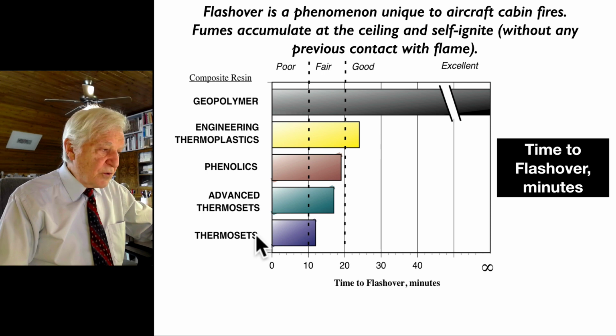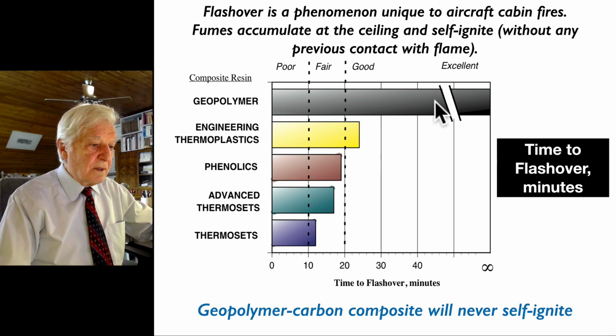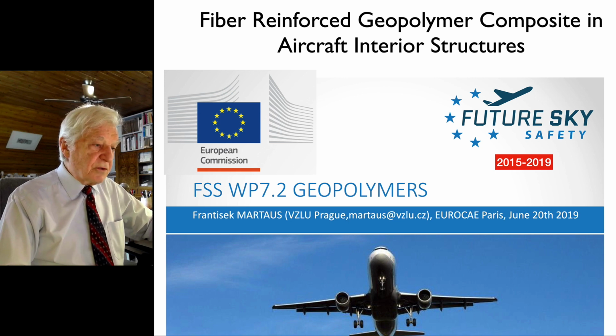The regular thermoset self-ignite at 12 minutes. Phenolics at 19 minutes. Geopolymer will never self-ignite, infinite time.